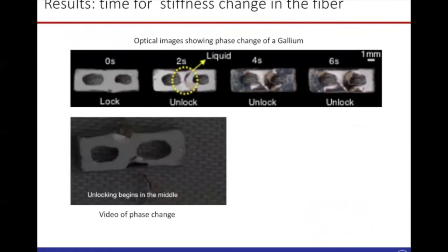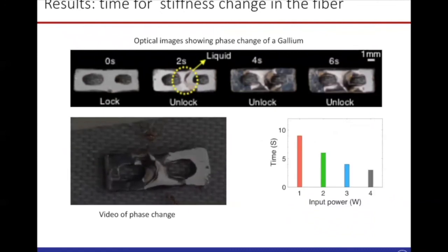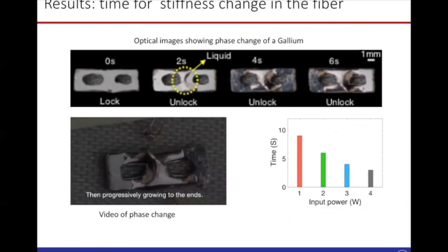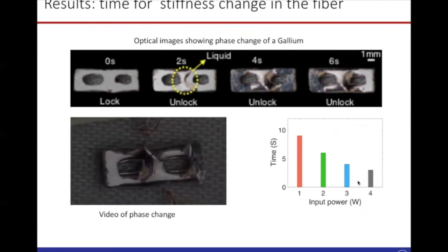Now let's quickly look into the time for the stiffness change. Here it shows the video of a phase change, and using this optical image, you can find out that we can unlock the soft part within 3 to 4 seconds using an input power of 3-4 watt. That's a small input power, and you can quickly unlock the soft part. Stiffness regain takes some time because it's a cooling process. Usually it takes 1 to 2 minutes. But yes, we need to improve that stiffness recovery stage in later studies.